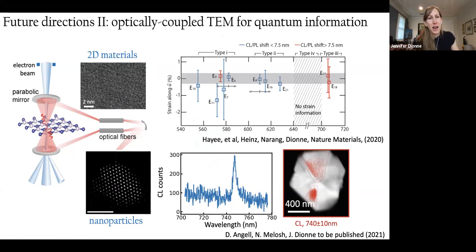And because optically coupled environmental electron microscopy gives us atomic scale resolution, we can start to look, for example, at silicon vacancy centers and nanoparticles and nanodiamonds, and also at various quantum optical defects in two-dimensional materials, and begin to understand how the atomic scale structure influences quantum optical emission and quantum coherence, and also use simultaneously the electron beam in various gaseous environments to deterministically place emitters. So I think this is an extremely exciting direction.